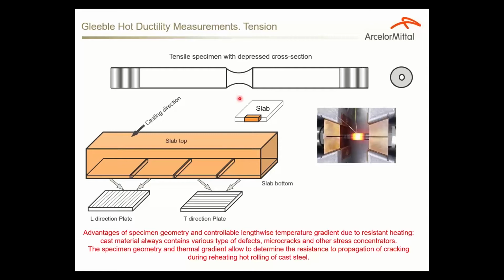Although this is not a very comprehensive tension testing, we see it as an advantage, because when the slabs crack, that means that there are already some defects, stress concentrators, present in the slab. So we are focusing on the localized deformation that gives us an idea why the slabs actually crack, not why the crack is initiated. So in our opinion, this kind of heating in the Gleeble is advantageous compared to uniform heating with an induction furnace or with a radiant furnace.